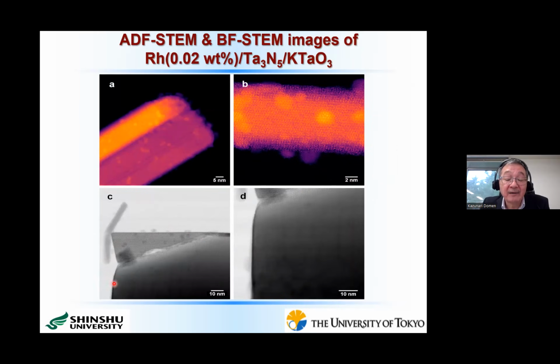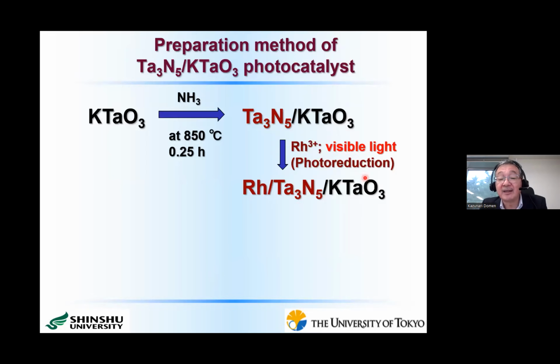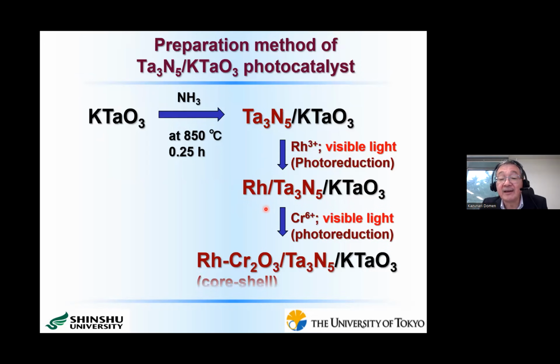And this is a more wide space, and then this part is potassium tantalate, but only these small particles are located only on this nanorod. That means that this structure is what we expected at this stage. Then to cover this surface area, we also used the chromium oxide layer, core shell structure again. And in this case, we didn't use any co-catalyst for O2 evolution.